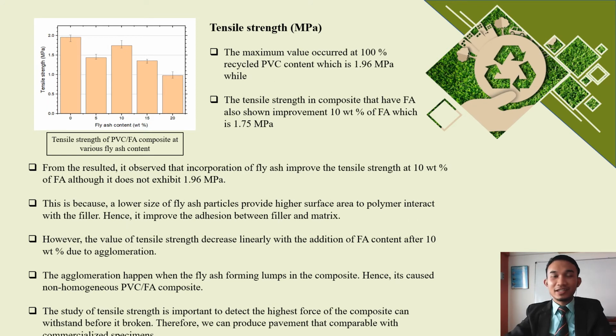Next, I will share the tensile strength of the composite. From the graph, we can observe that the maximum value occurred at 100% recycled PVC content, which is 1.96 megapascal. The tensile strength in the composite that has fly ash also shows improvement at 10 weight percentage of fly ash, which is 1.75 megapascal. From the result, it is observed that incorporation of fly ash improved the tensile strength at 10 weight percentage of fly ash, although it does not exhibit 1.96 megapascal.